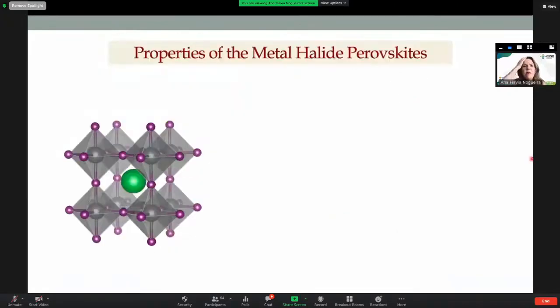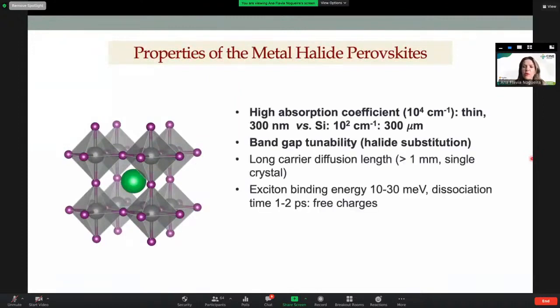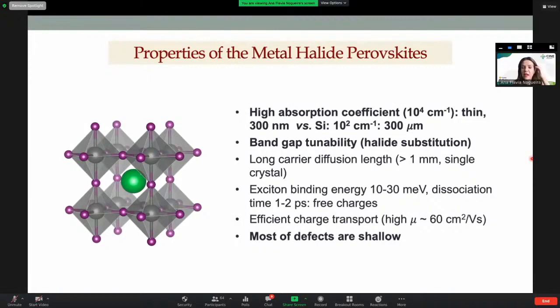In terms of the properties of the metal halide perovskite, there are many properties. I'm going to just cite some of them. For instance, they have a really high absorption coefficient that is much higher than silicon, like two orders of magnitude higher. It means that you can make this device, at least the active layer, very, very thin, in the order of 300 nanometers. You can also tune the band gap, not only by playing with the halide compositions, like changing the ratio between bromide and iodide, but also by playing with the organic cation. Another interesting property in this material is that most of the defects, of course, the perovskites have many defects, but these defects are shallow, I mean, are not harmful.